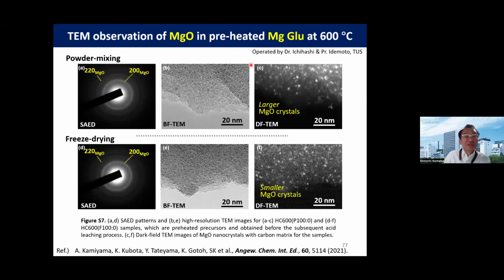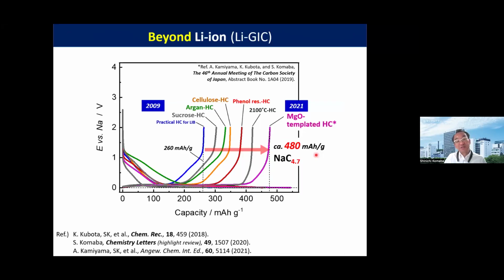Actually, from the TEM observation, the freeze drying was a successful method. From a dark field image, we can see that very small particles are well dispersed in the carbon matrix. This is direct evidence of the formation of magnesium oxide nanocrystals in hard carbon. The size is about one or two or a few nanometers in diameter. So after post-heat treatment, we can remove this magnesium oxide, and the reversible capacity is here.